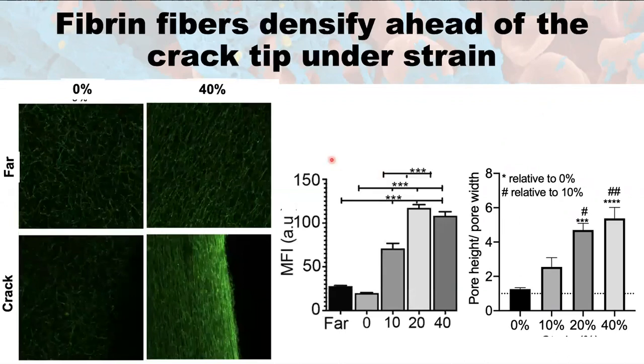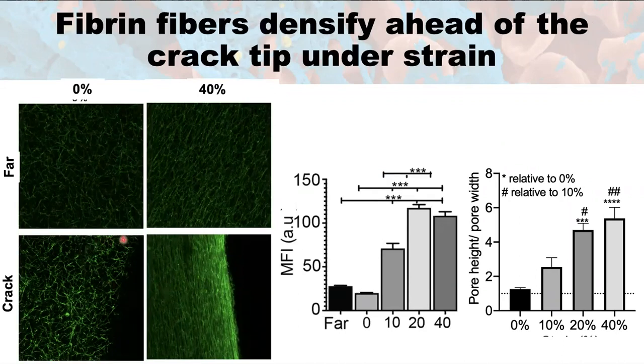We also note that there is densification of the fibrin fibers ahead of the crack tip. So we're able to look at this densification again in these same confocal images through two different analysis methods. One, we see that there's an increase in the mean fluorescence intensity under increasing strain compared to both regions far removed from the crack tip and those that are not under strain, showing that there's an increase in that fibrin density. In addition, we're able to look at the pore sizes within the fibrin network. And if we look at the ratio of the pore height to the pore width, we see that that changes as we increase the amount of strain on the sample, again pointing to a change in the structure of the clot where the fibers start to come closer together, resulting in their densification.